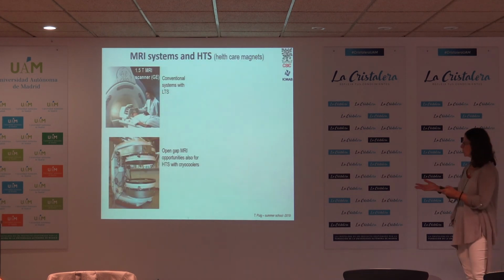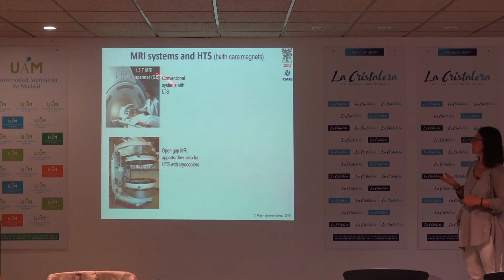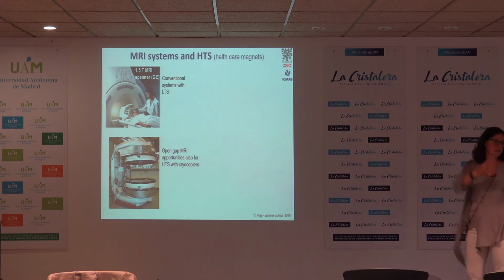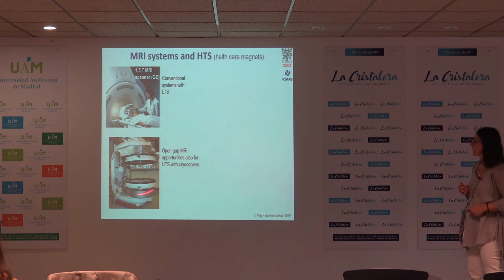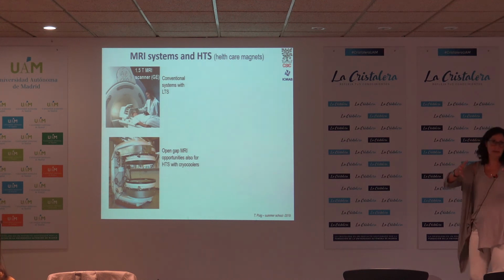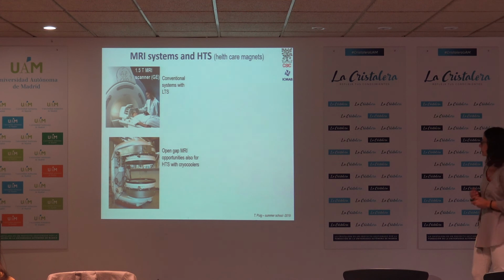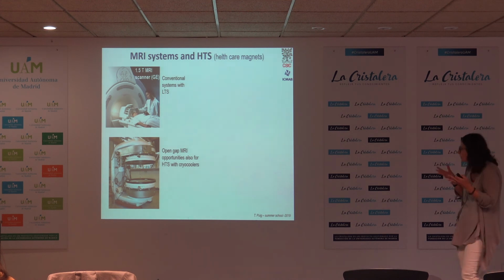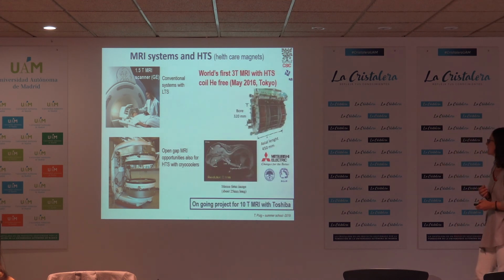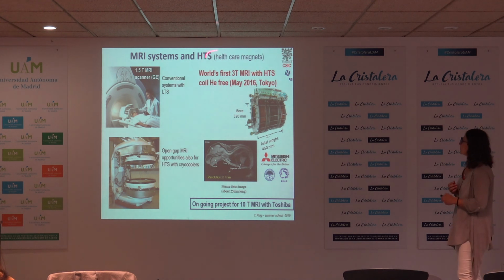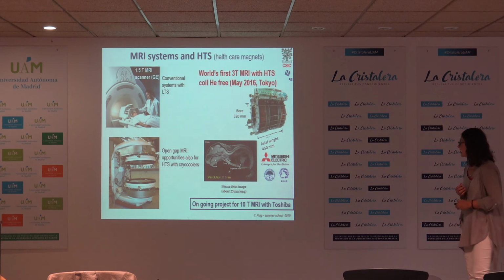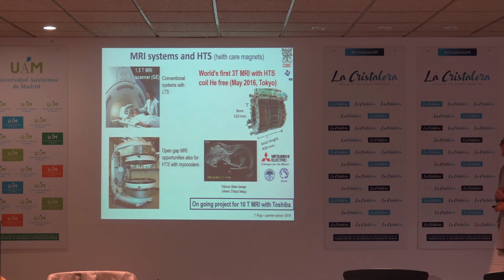And in MRI also, of course, the conventional MRI that we get in all the hospitals is around 1.5 Tesla. This is niobium titanium. HTS is now opening the possibility of open-gap MRI, so that you don't have to go into a tunnel, and you don't feel the closed environment. But also there has been demonstrated already a 3 Tesla MRI with HTS to really go beyond the 1.5. This is at Toshiba.